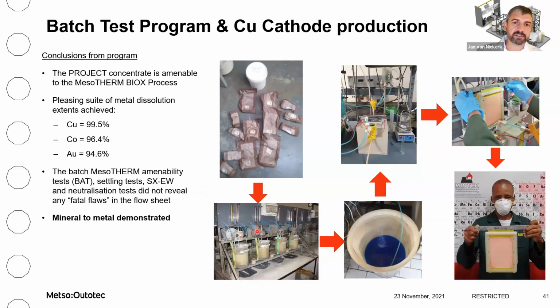Yeah, we followed the process and did each step of the process. Some of the results were very pleasing. We achieved a copper dissolution of 99.5%, cobalt of 96, and gold of just under 95. So it really demonstrated the process, and it showed that there's no real fatal flaws in the process. Yeah, a really, really nice set of results.